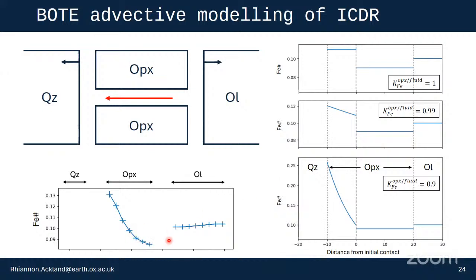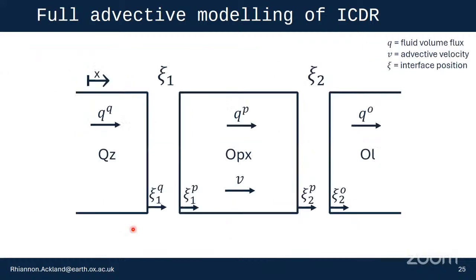And some of my rims show maybe a clearer signature of flattening out towards the olivine interface. And obviously with the probe, the excitation volume means that these profiles are slightly smeared. And so one of my next steps is to consider a more quantitative, detailed model of this reaction, where the OPX interface is allowed to move at a different rate to the quartz or olivine interface. This allows us to express the volume change of the reaction and the creation of void space, with the orthopyroxene allowed to advect within this void space to control where it's opening up. And due to the inclusion of void space, you can express the fluid volume flux within the OPX region and also from the quartz and olivine into the void space.